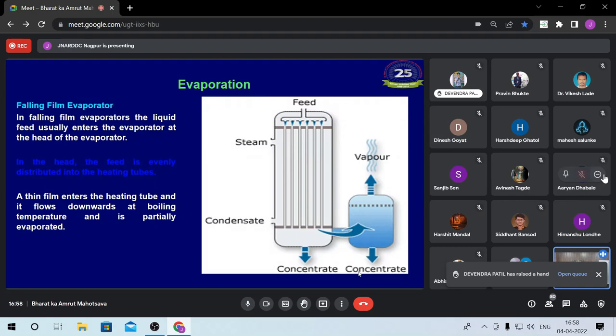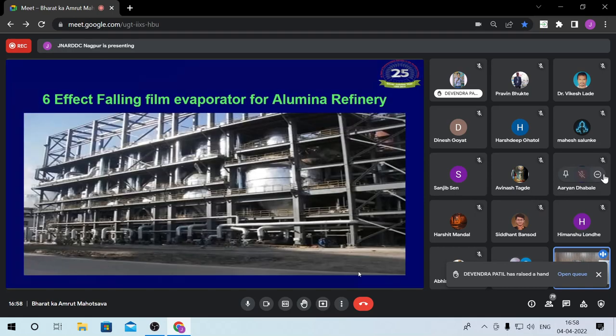Now, evaporation with a single stage is not going to give you a very high efficiency. So that's why normally 6 effect falling film evaporators are used in the alumina refinery, and these give an advantage in the steam economy, that is 1 ton of steam is going to remove around 3.5 tons of water which is evaporated. So with 6 effect falling film evaporators you are going to get almost 3.5 times more as compared to a conventional evaporator.